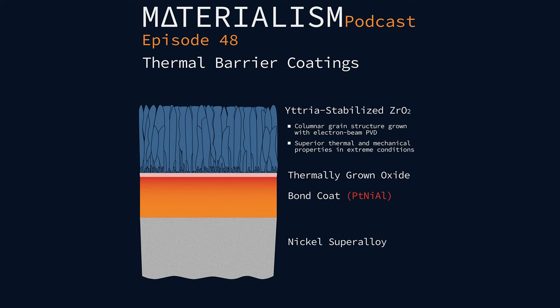Yeah, think about it. You have things heating up and cooling down. Over time, you're going to be putting a lot of strain on the materials, which translates to stress as well. And when materials undergo stress, they tend to want to eventually relax that stress. They want to remove it because it's a high energy state. It's not favorable. And so one way to relax that is to change your dimensions. So essentially what they had happening was these stresses on these interfacial layers would cause buckling to occur. And so you'd get this nice ribbon, almost like a sine wave, that would form between the alloy and your ceramic coating.